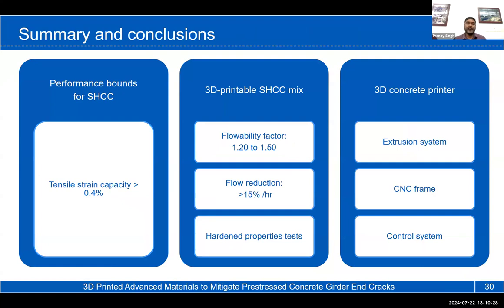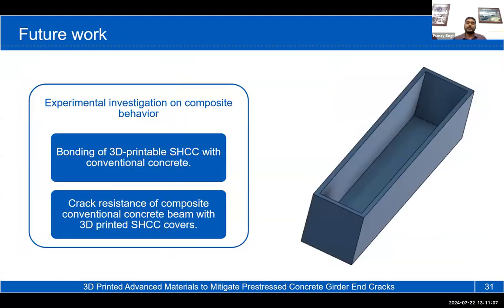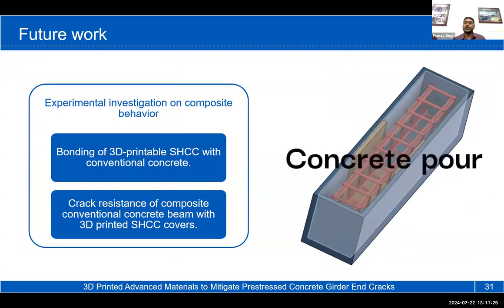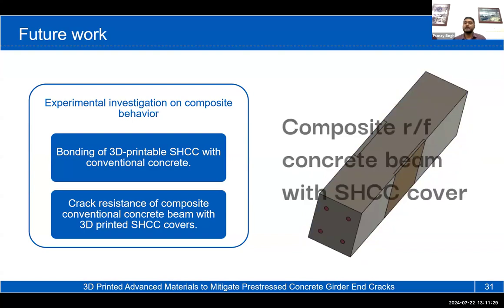In summary, we established the performance requirement in terms of tensile strain capacity for our strain hardening cementitious composites, and it was found to be greater than 0.4%. We did some experimental investigation to come up with the rheological requirement using the drop table test, and we found the suitable flowability factor to be around 1.2 to 1.5 and flow reduction to be greater than 15% per hour. We performed hardened property tests as well and found that the mixes were complying with the requirements. We further developed a 3D concrete printer with an extrusion system, CNC frame, and a control system. For future work, we are investigating the bonding of the 3D printable SHCC with conventional concrete and the crack resistance of the composite conventional concrete beam with a 3D printed SHCC cover. We are trying to test this idea of using 3D printed SHCC as a permanent formwork in beams.